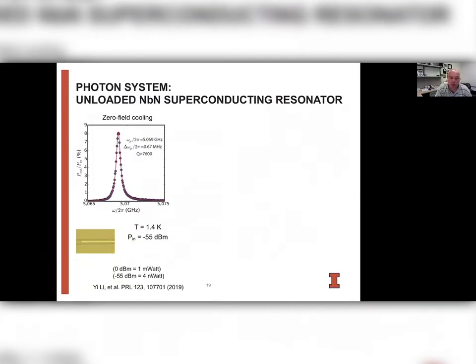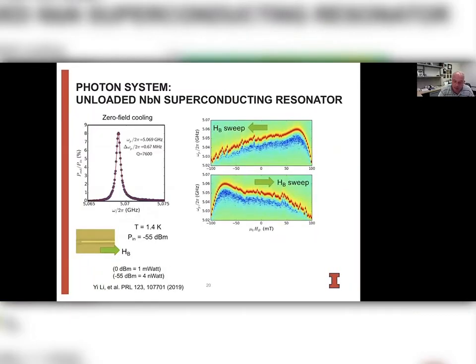Now, first, what we do is we characterize our superconducting resonator without the permalloy structure. And so what you see here is a transmission measured as a function of frequency at 1.4 Kelvin with relatively low power of minus 55 dBm, which is equivalent to 4 nanowatts. What you see, we have a quality factor of almost 10,000, so roughly 7,500. So we have a line width of half a megahertz at a resonant frequency of 5 gigahertz.